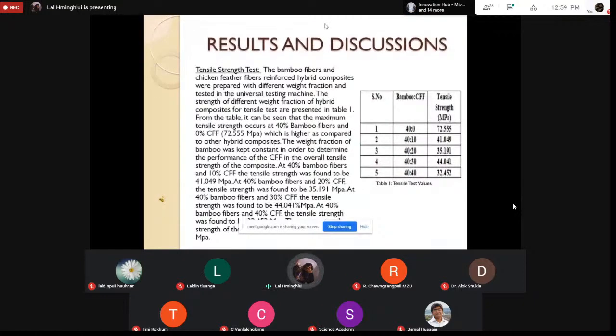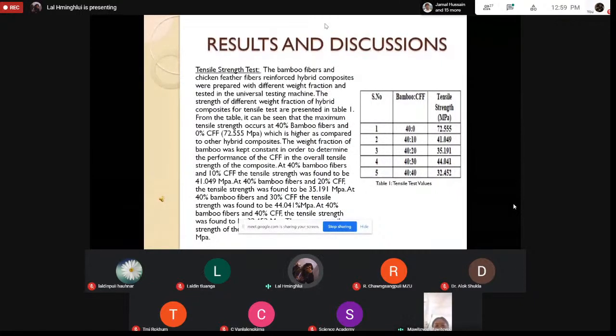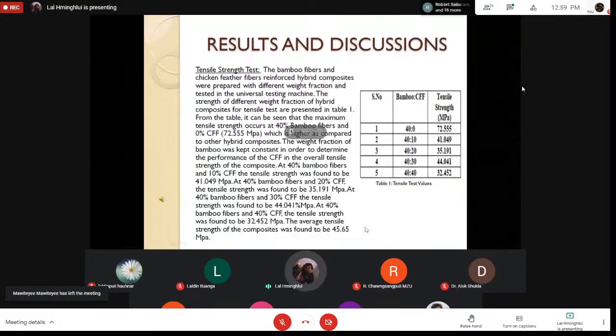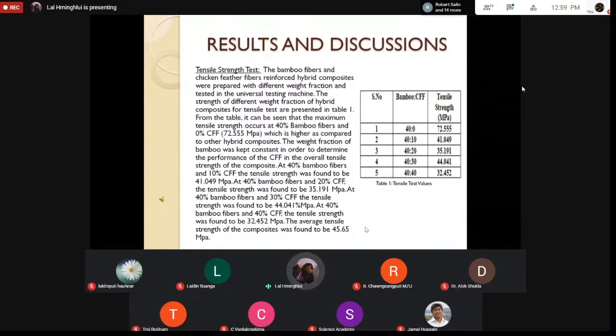So in table number 1, we have the tensile test values. The bamboo fiber and chicken feather fiber reinforced hybrid composites were prepared with different weight fractions. They were tested by using the universal testing machine. From the table, we can see that at 40% bamboo fiber and 0% chicken feather fiber, the tensile strength was observed to be 72.555 megapascals. And at 40% bamboo fibers and 10% chicken feather fibers, it was found to be 41.049, and so on. And the average tensile strength of the composites was found to be 45.65 megapascals.